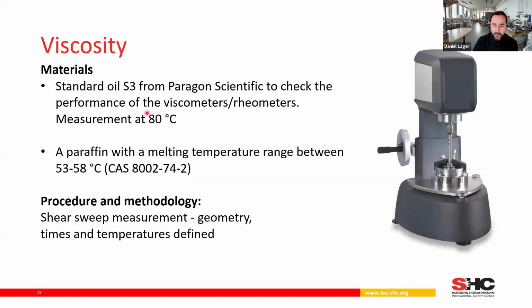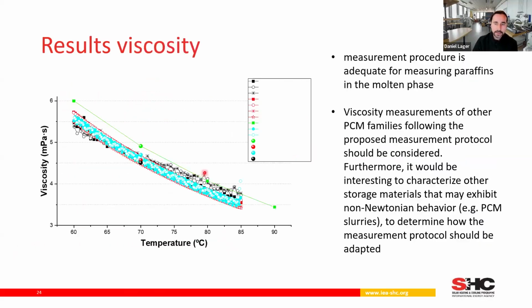Last but not least, viscosity measurements. For the viscosity measurements, we also used the same paraffin wax, but we additionally used the standard oil so that we also have a reference material in the round robin test. And here we measured with shear sweep measurements. So geometry was defined, the times were defined, and also the temperatures were defined.